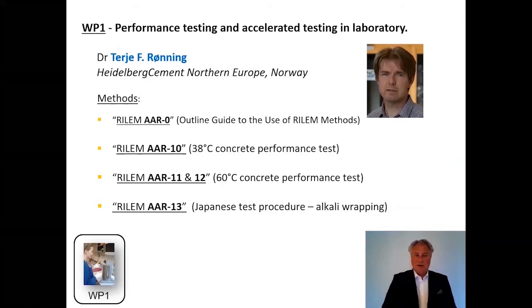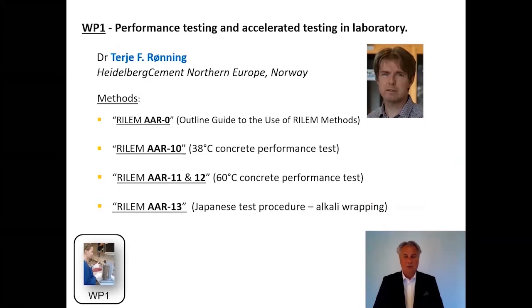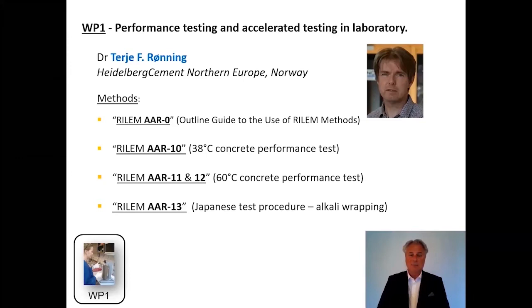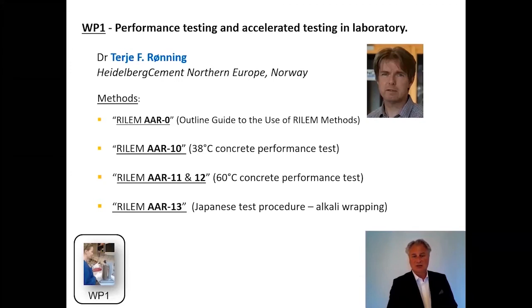The first work package was led by Dr. Terje Rønning from Heidelberg Cement Northern Europe, looking into performance testing and accelerated testing in the laboratory. We revised the RILEM AAR-0 document, which is an outline guide to the use of RILEM methods. In addition, we developed a new concrete prism test called AAR10 at 38 degrees, two new concrete prism tests AAR11 and AAR12 with exposure at 60 degrees, and RILEM AAR13 based on a Japanese test approach where concrete prisms are wrapped with an alkali solution to counteract leaching.